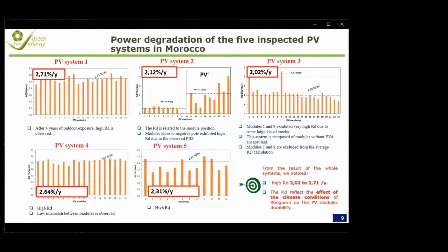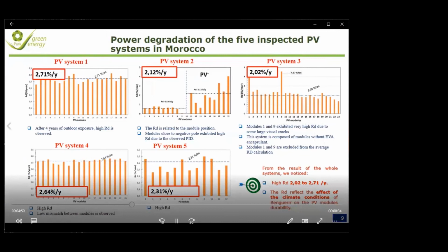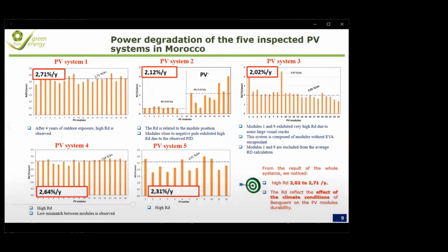For the results of the power degradation of the 5 inspected PV systems in Morocco, these figures show the individual power degradation rate for the PV modules of each selected string, as well as the average degradation rate. As clearly seen, for the 5 systems, all the PV systems show high degradation rates. So this result does not compare favorably with that given by the manufacturer, with 0.8% per year as an average degradation rate for crystalline technology.